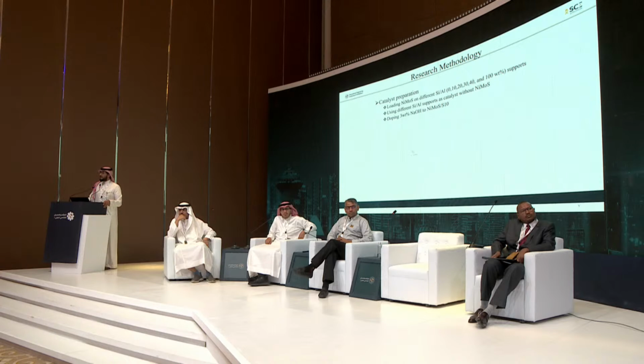The research methodology. As for the research methodology, we have the catalyst preparation. What we have done is that we loaded the nickel molybdenum sulfide catalyst on different supports that vary in their silica alumina ratio from 0 to 100%. And we tested for the hydrogenation and dimerization of 4-methylstyrene, and we'll talk about the model compound in a bit. The second one, we took away the nickel molybdenum catalyst, and we used only the supports, to see the effect of only the support in the hydrogenation dimerization reaction. The last thing is that we added NaOH base to kill the acid sites and see if it makes any improvement for the catalyst activity.